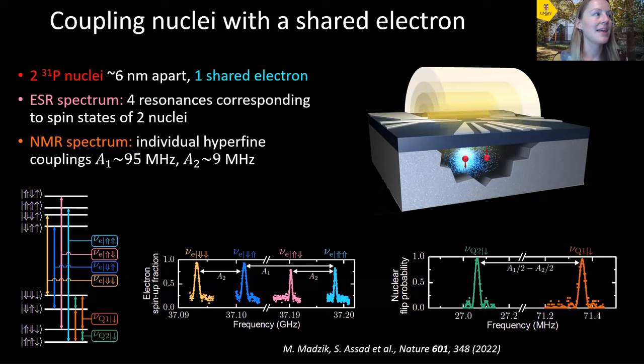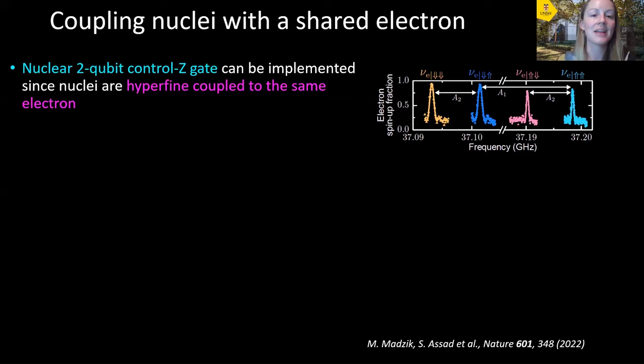And then if you look at the nuclear magnetic resonance spectrum, it shows 2 peaks that allows us to extract the individual hyperfine couplings between each nuclei and this shared electron. And in this device, we saw that the electron was more tightly bound to the donor nucleus on the left because we measured a much larger hyperfine coupling to the nucleus on the left than on the right. And so we can implement a 2-qubit control Z gate on this device between the two nuclei because they share this same hyperfine coupled electron.